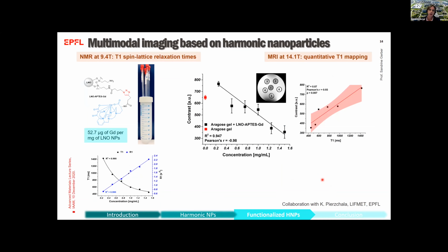So then we went to further analysis of those nanomaterials for MRI imaging. At 9.4 Tesla, we analyzed the T1 spin lattice relaxation times using a phantom based on an agarose gel, with 6 different concentrations of those nanoparticles in suspension. Here you can see the clear dependence of the T1 spin lattice relaxation time on the concentration of the nanoparticles in the suspension.